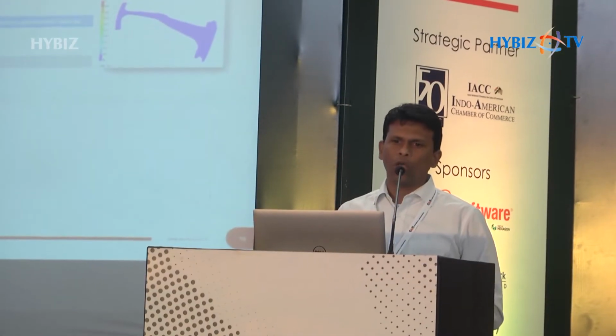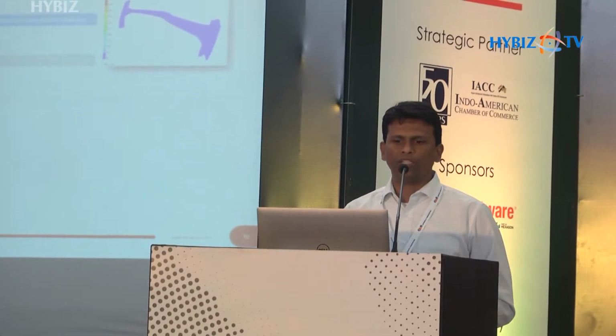So once we have the preform ready, we would be able to directly take it to the autoclave and then do distortion analysis, or you could take it to the RTM process and then do various kinds of RTM process like RTM or VARI or light RTM process, SERTM process, HPRTM process, to see what is the best way of injections, location of injection gates, location of vents, and then position on the size of the flow, and if you want to adapt to a heated mold or something like that.